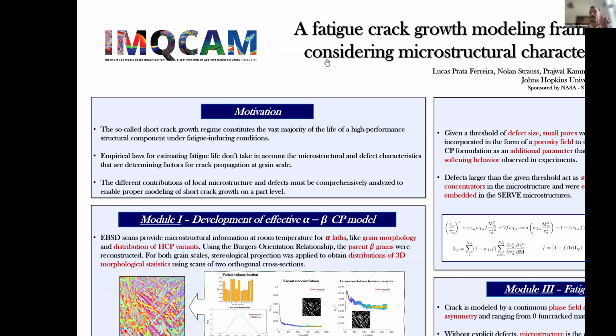However, whenever we model fatigue, so we estimate the fatigue life of the materials using Paris law or some other model, these are just empirical equations that don't take into account the microstructural characteristics, which are the driving factors for short crack growth. Especially in additively manufactured materials like with laser powder bed fusion, we have high variability of the fatigue life of components.